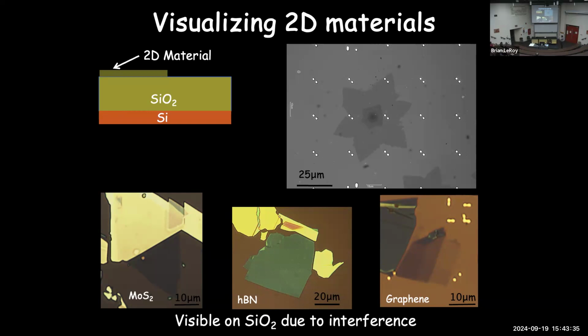So here's an example of a piece of graphene on a silicon oxide substrate, and you can very clearly see this is silicon oxide here. The kind of flower pattern is a monolayer of graphene. The next one in is 2 layers, and then 3 layers that get slightly darker inside. And so basically, just by looking at the contrast or the color, if this was not a black and white image, you can see how thick your material is. And the same thing will apply to these other materials.